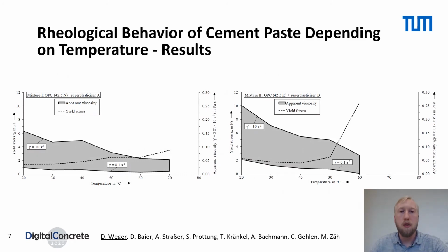We measured the rheological properties with a double plate geometry with a descending step profile at temperatures between 20 degrees Celsius and 70 degrees Celsius in increments of 10 degrees. The yield stress and the apparent viscosity were determined using the Herschel-Bulkley model, and each measurement was done 15 minutes after addition of water. Now let's have a look at the results of the measurements of mixture 1 on the left and mixture 2 on the right.